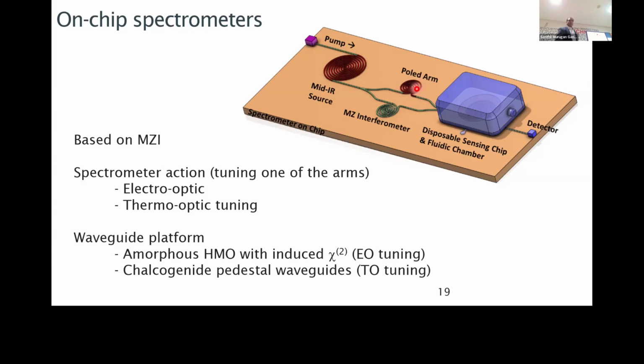And the refractive index change can happen in two ways. One, using the electro-optic effect by applying an electric field. Then you change the refractive index of the material. Therefore, the path length on one side is changed. The other way is to introduce heat. That is using the thermo-optic effect, where the refractive index is changed as a function of temperature. So these are the two principles we used and developed two different platforms.